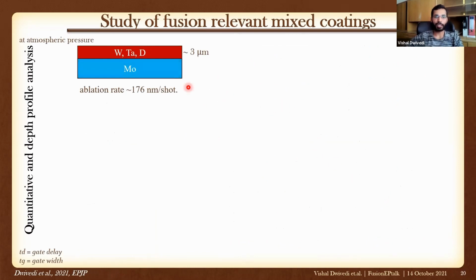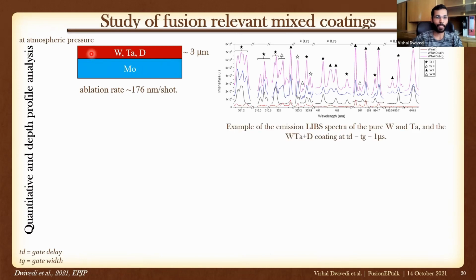After that, we studied a tungsten, tantalum, and deuterium coating on a molybdenum substrate. It was 3 micrometers, and the ablation rate was found to be around 176 nanometer. This was measured at atmospheric pressure in our lab in Bratislava. This was the spectra. We tried to measure firstly pure tantalum to see the tantalum lines, here in black color. After that, we tried to measure pure tungsten, in red color here, and we can clearly see the difference between tungsten and tantalum lines. After that, we measured this specific coating.